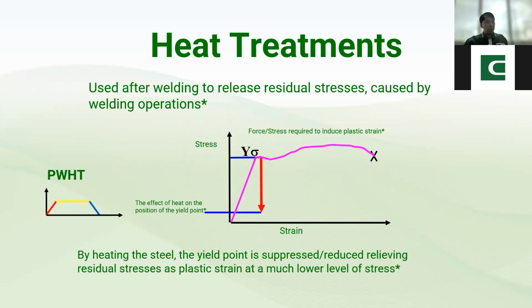The post-weld heat treatment. So, aalisin natin yung residual stress na trap sa ating weldment during welding operation. Dahan-dahan nating iinitan, slow heating, then soak at 600 degrees centigrade, and then slow cooling in order for you to release residual stress on our weldment. This one I discussed thoroughly.